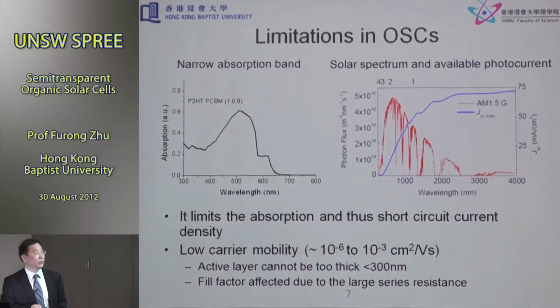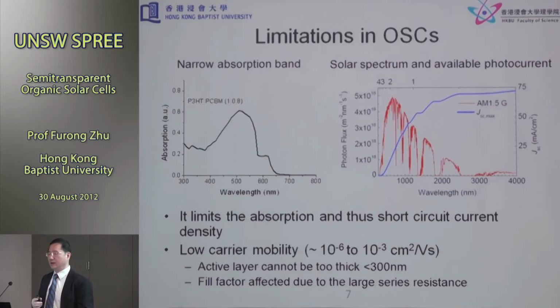Here I'm sharing with you some of the main difficulties or limitations organic solar cells face at the moment. Mainly, as I mentioned, P3HT:PCBM. This is the main system that people have widely reported. In the beginning of the work, we chose this system because there is a large amount of data available for comparison studies, and you will see that it has a relatively narrow absorption spectrum, and although the material itself has a relatively high absorption coefficient, the maximum output photocurrent density depends on the absorbance.